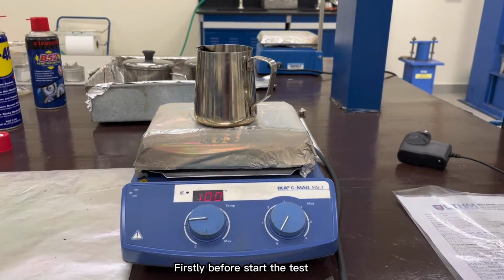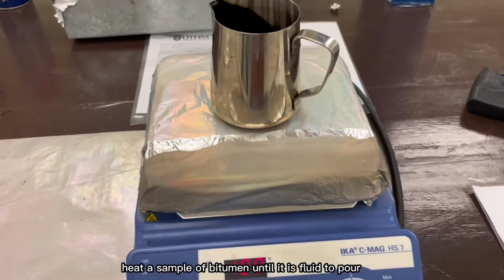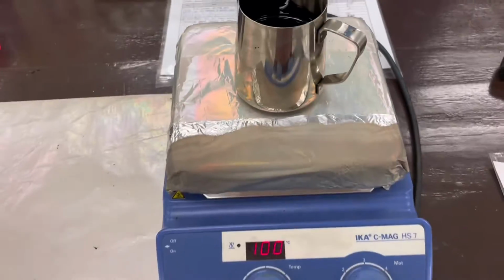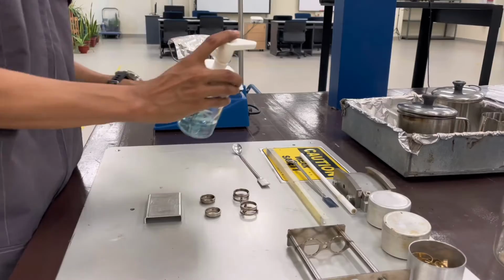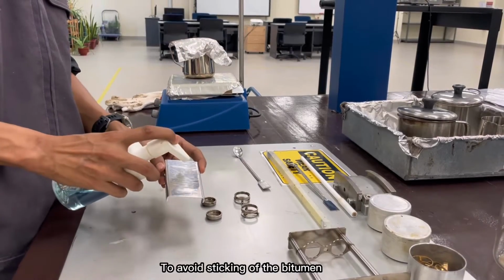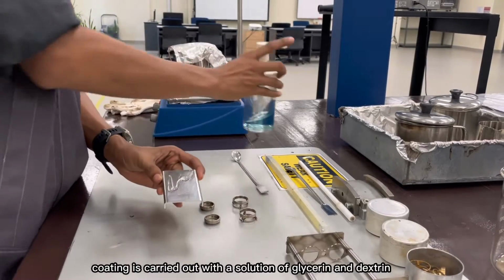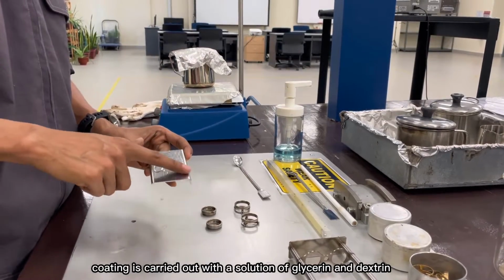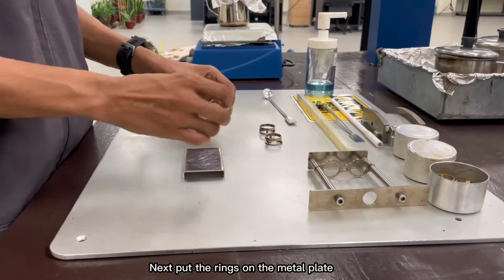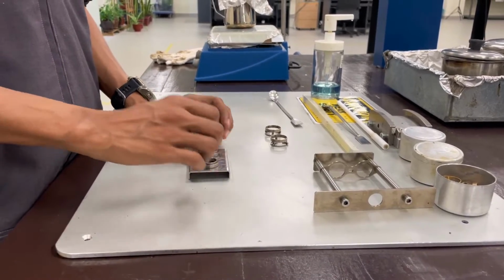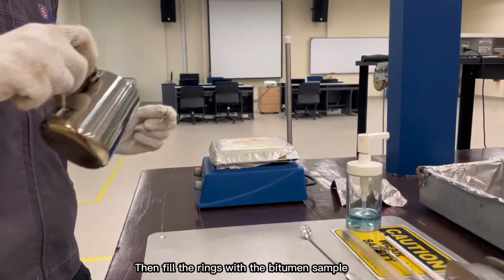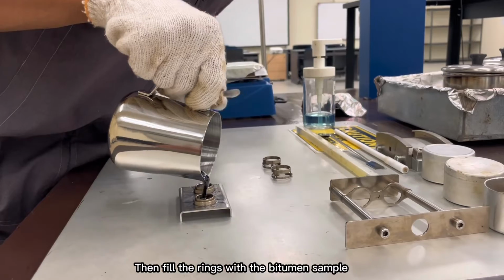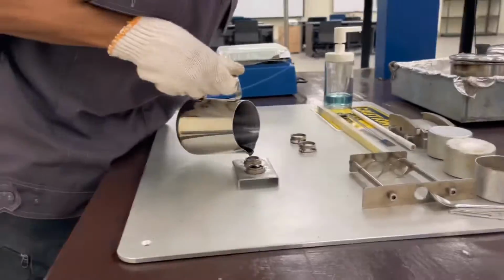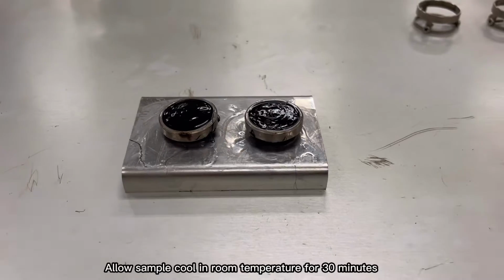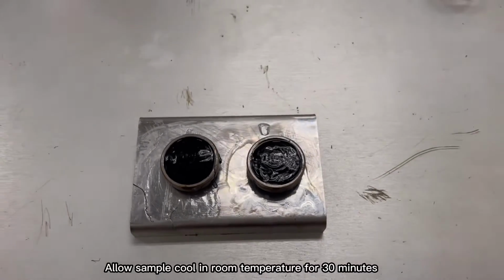Firstly, before starting the test, heat a sample of bitumen until it is fluid enough to pour. To avoid sticking of the bitumen to the metal plate, coating is carried out with a solution of glycerin and dextrin. Next, put the rings on the metal plate. Then, fill the rings with the bitumen sample. Allow the sample to cool at room temperature for 30 minutes.